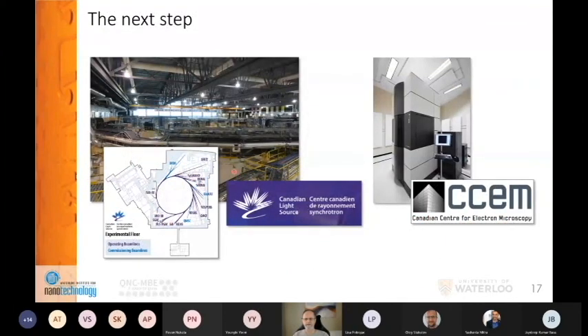And the nice thing about the X-ray is it's non-destructive, and then we can use the same sample for doing high-resolution transmission electron microscopy at the Canadian Centre for Electron Microscopy, which is going to elucidate how those interfaces really look, and hopefully we will be able to eliminate the uncertainties which are inherently present with the TEM due to the sample preparation and also just the energy of the electrons bumping into those not so hard materials.